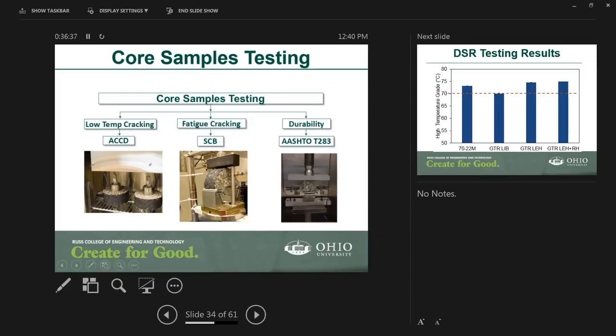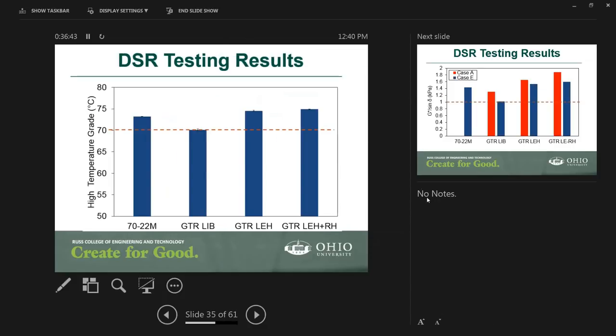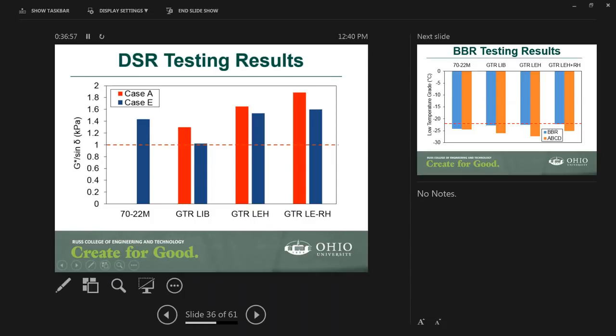In terms of high temperature, as you can see, all binders met the 70 minus 22 target, or rather the 70 high temperature grade. This figure is showing the G star over sine delta, which is used as the criteria to determine your high temperature grade. And again, the criterion is that the G star over sine delta should be one.